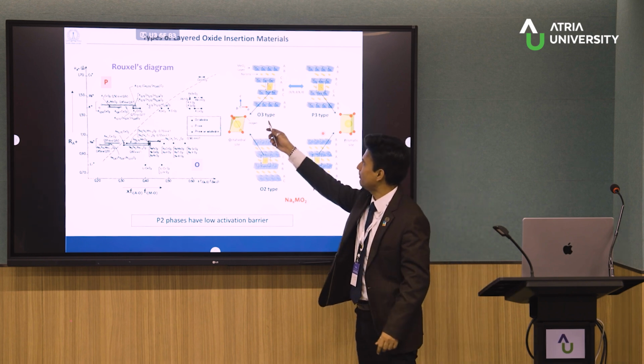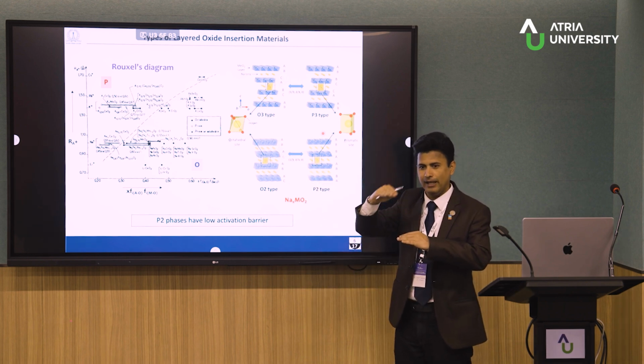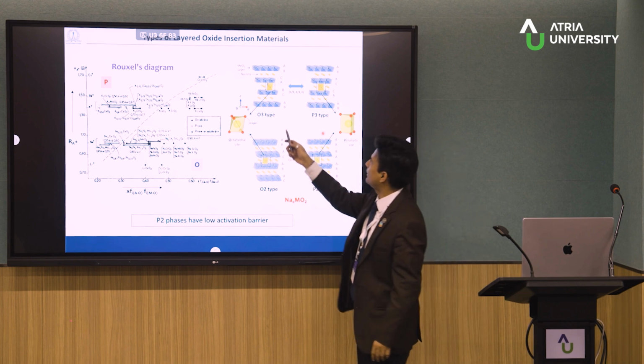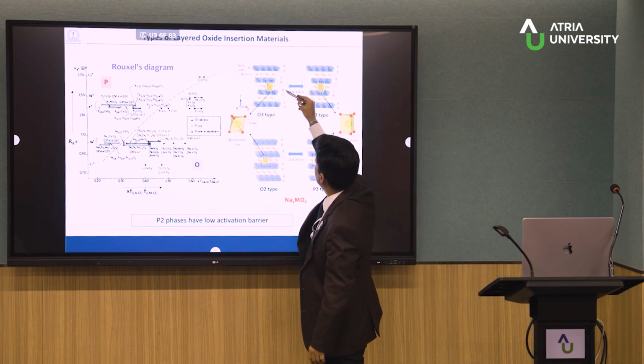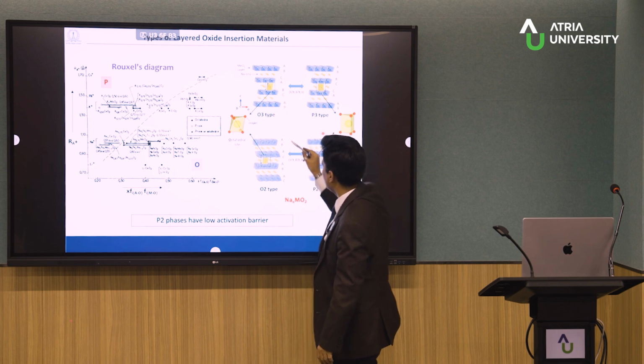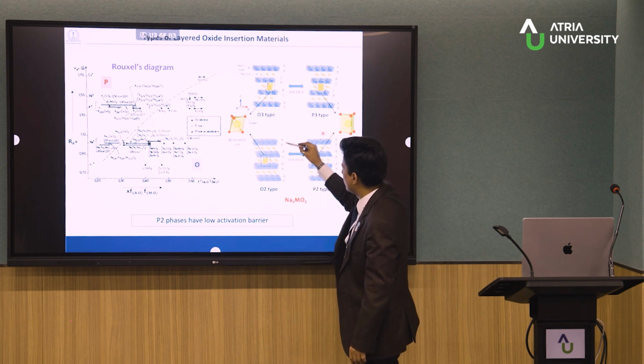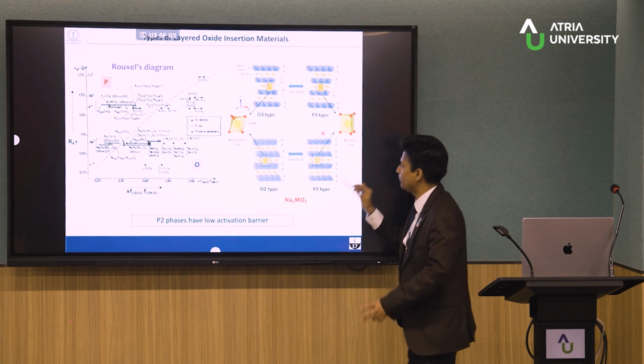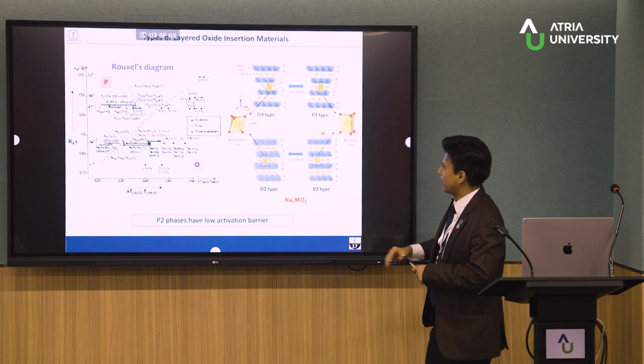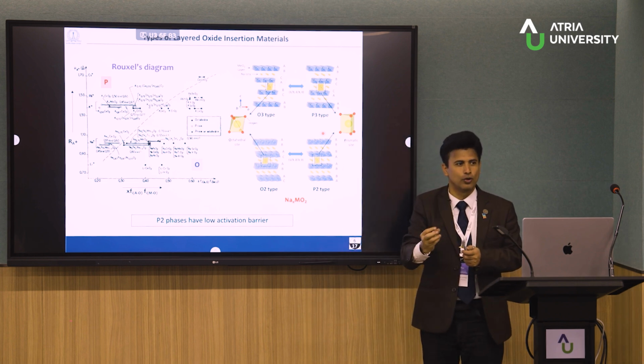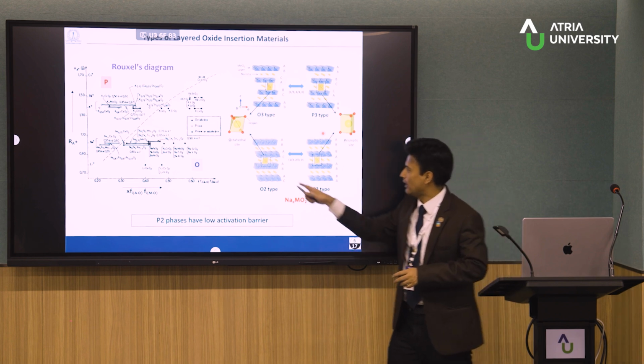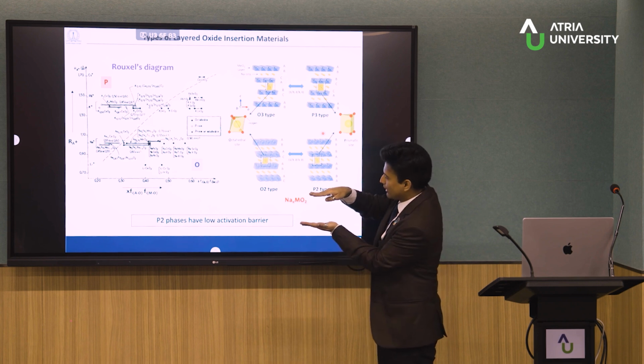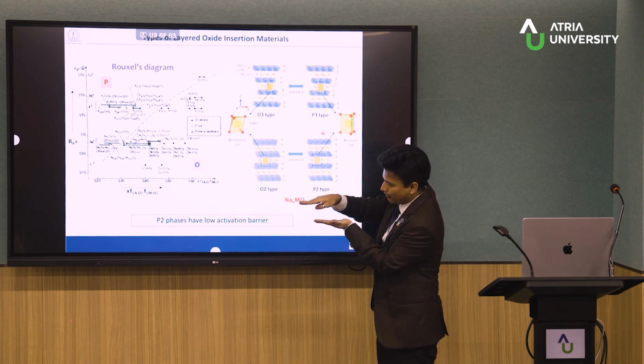And the number here basically denotes after how many layers it repeats again. So this is A, B, C, A, B, C, A, B. After 1, 2, 3 layers, again A, B repeats. A, B, A, C, A, B, A, C. After 2 layers, 1, 2, again A, B repeats. So that's for 2. That's why it is P2, P3, O2, O3. Among them, if I just tell in fluid language, what is the octahedron? In the octahedron, basically the two transition metal layers are looking away from each other.